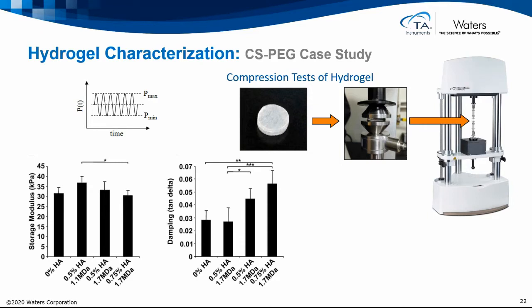What's interesting in this additional analysis is you can look at the damping. This damping term, tan delta, is a measure of the force plot, that sine wave of force, and the sine wave of displacement. Any phase delay in what's called a DMA assessment, or a viscoelastic assessment, shows you the viscous portion. As that delay gets more and more, the tangent delta gets larger, which means it's a more viscous material. If there's very little damping, it's more like a spring, with very little viscous behavior.